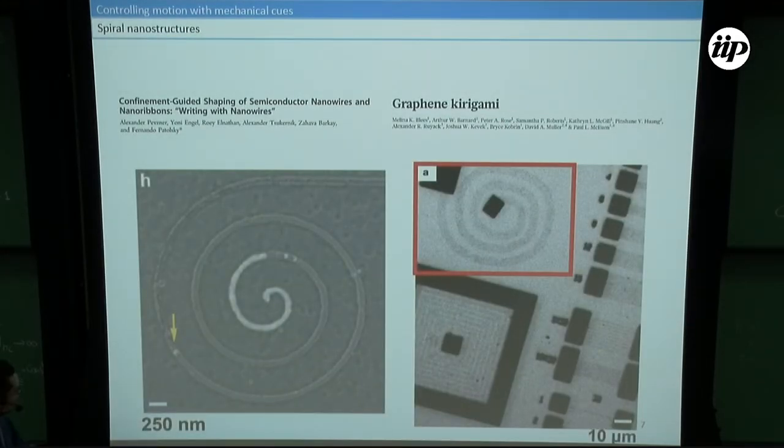So the structures that they have curvature in the experiments are much larger, so the curvature gradient will be much smaller than what we have in the simulation. But I think this is not as bad, as long as we can put some graphene that has some incommensurate orientation. That should be okay because the friction is basically zero. So even if the curvature is smaller because the radius of the spiral is much bigger, you still can get some movement because the friction is very, very low.